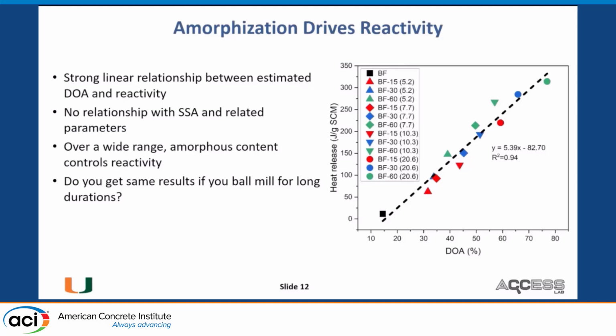However, here's my thinking. I think the reactivity is driven by the amorphous content, because basically you can take inert powder and you can start to size fractionate it, but unless you get to nano sizes or something, if something is inert, it generally will stay inert regardless of what the specific surface area is, within certain limits. In this case, what I think happens is that beyond 15 minutes, the specific surface area is really not changing. So that increase in reactivity because of the specific surface area is largely controlled by what happens in the first 15 minutes.